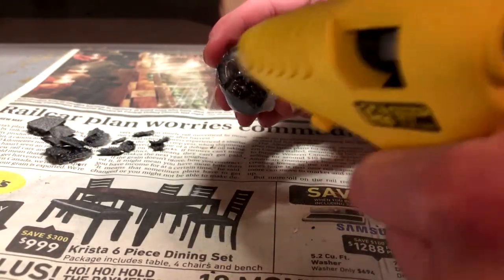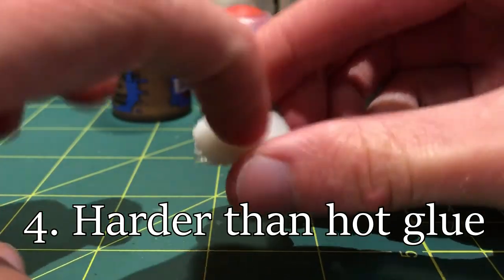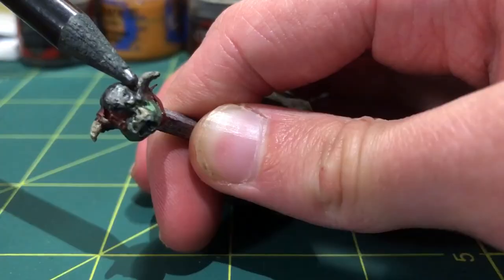Now it's time to discuss the pros and cons of white glue casting. Firstly, the pros: white glue is ridiculously cheap — you can get a bottle for three or four dollars and there's a lot of glue in each bottle. Using the same molds as hot glue casting means you don't have to risk ruining your miniatures again. The drying process can be sped up by leaving pieces to dry in the sun. Because the white glue castings are hard after fully drying, it may actually be a better material for creating full miniatures with several parts than the much more squishy and flexible hot glue. White glue may also be better at preserving details just because it's a slow-drying liquid compared to a fast-drying thermoplastic — just take a look at this orc helmet where you can clearly see a rivet preserved in the casting. And just like with hot glue casting, these pieces can be used for painting practice, spare parts, and are perfect for terrain without consuming your good bits.